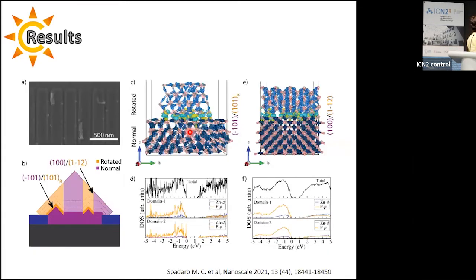But we wanted to investigate the effect of this type of domain on the photovoltaic application. Therefore, we were interested in studying the electronic properties of the material in presence of this domain. For this reason, in collaboration with Cardiff University, we could perform this density functional theory simulation, observing that the density of states of the material in presence of that domain is similar, is stable, as in the case the domains are absent. In fact, there are no dangling bonds and no mid-gap states that could provide the recombination of the carriers.